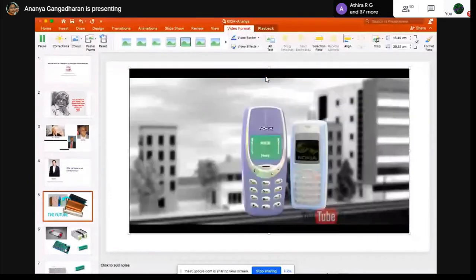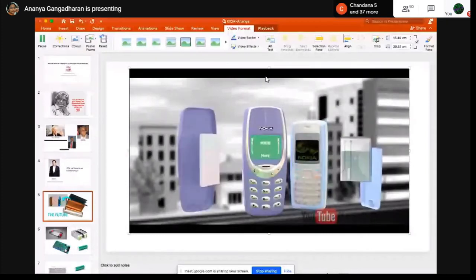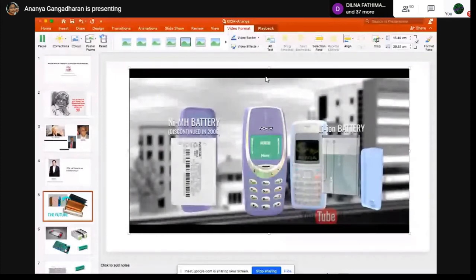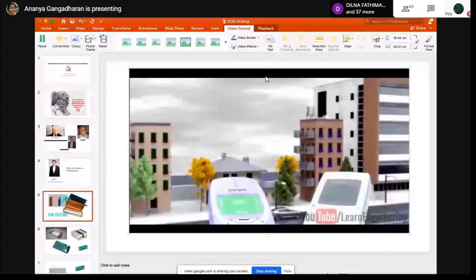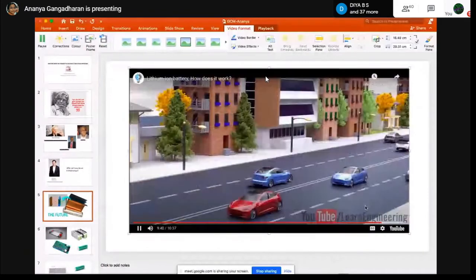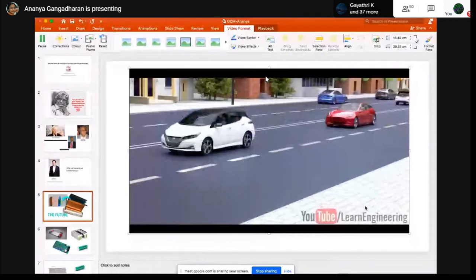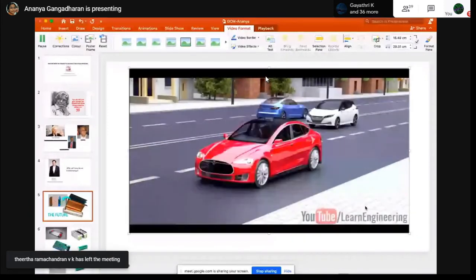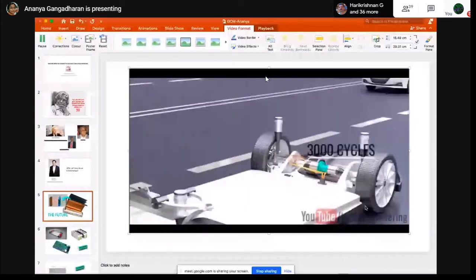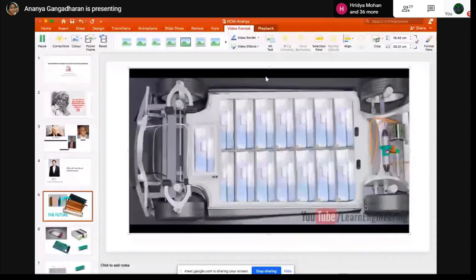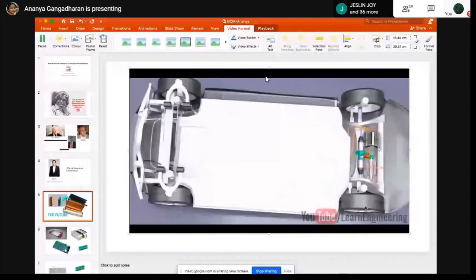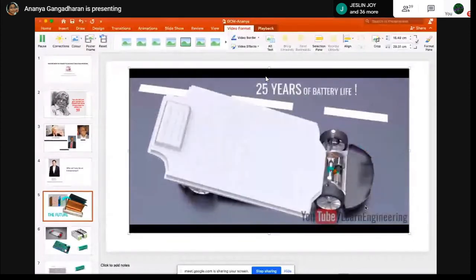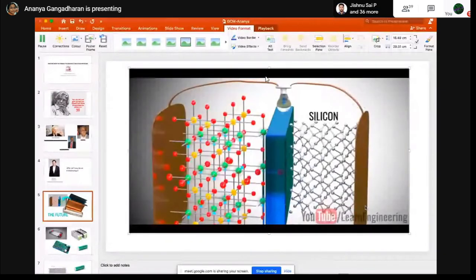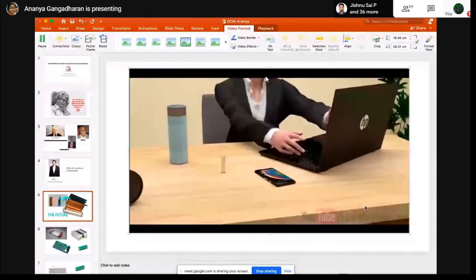It is amazing to find out that those electronic gadgets we used around 2 decades back did not use lithium-ion batteries. With its amazing speed of growth, the lithium-ion battery market is expected to become a $90 billion annual industry within a few years. The currently achieved number of charge-discharge cycles of a lithium-ion battery is around 3,000. Great minds across the globe are putting their best efforts into increasing this to 10,000 cycles. That means you would not have to worry about replacing the battery in your car for 25 years. Millions of dollars have already been invested in research into replacing the storage medium graphite with silicon. If this is successful, the energy density of the lithium ion cell will increase by more than 5 times. We hope this video provided you with a clear conceptual understanding about lithium.